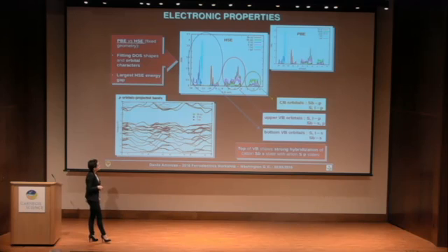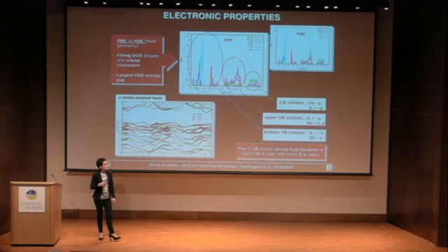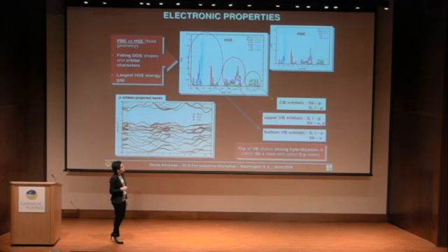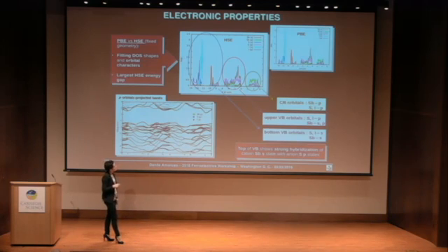So we can also characterize the compound from an electronic point of view. Looking at the density of states, and in particular at the projection of the orbital characters, we can state that the s levels of sulfur and iodine atoms are strongly localized in the lower part of the valence band, whereas an interesting mixing of characters is present in the upper part of the valence band.